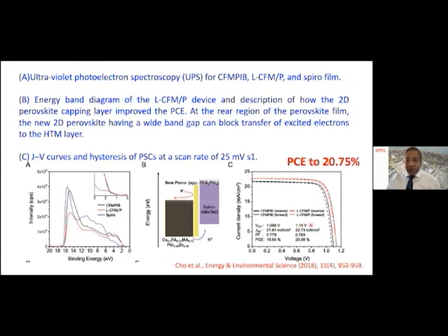And increased VOC with a small increase in the current gives you the high power conversion efficiency. And the champion cell is close to 21% power conversion efficiency. This is based on phenylethylamine, PEA, shown here as a two-dimensional perovskite interlayer between the three-dimensional perovskite and hole transporting material. So this is what we call interface engineering.